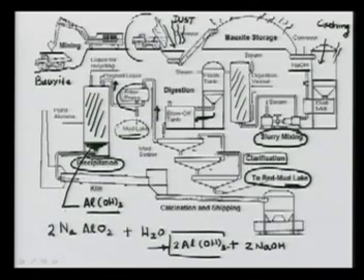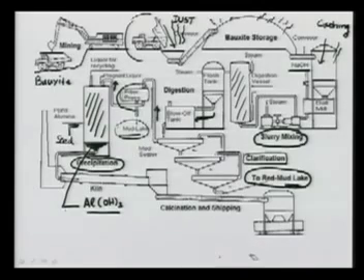Let's see then where do we go from here. Sometimes, because this solution of sodium aluminate is supersaturated, we put some seed here, seed that will help in the precipitation. So the precipitation of alumina or some seed is also added. Seed is nothing but again Al(OH)3.